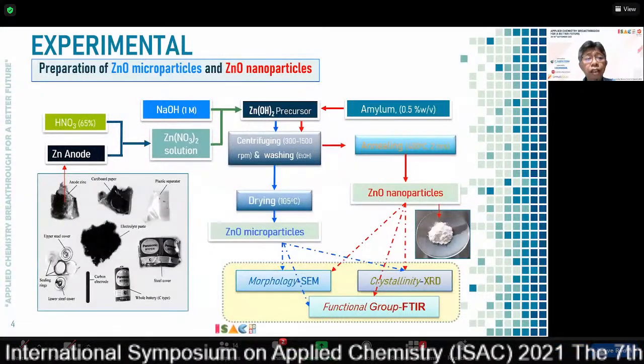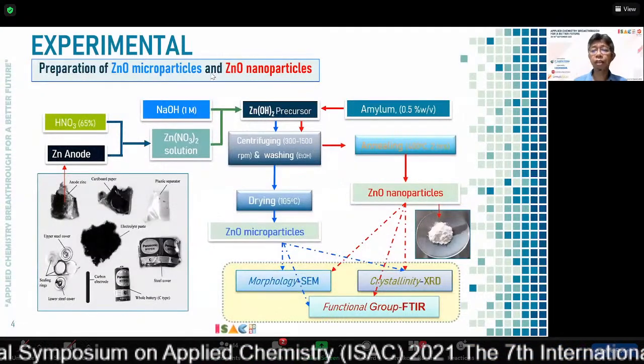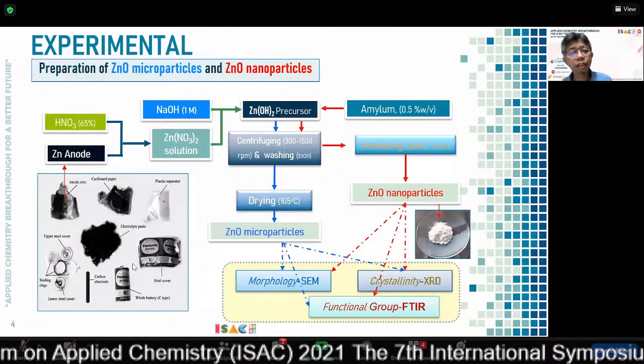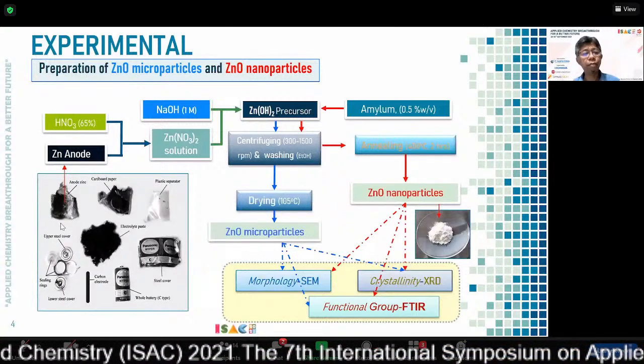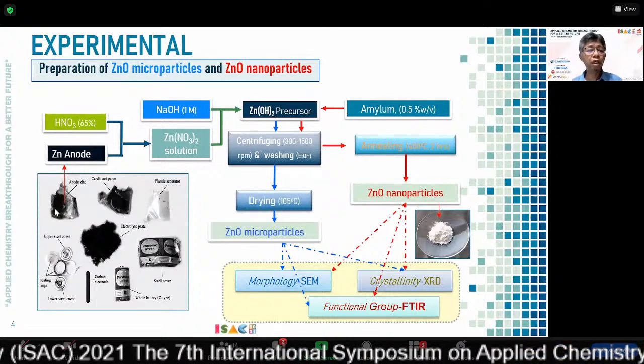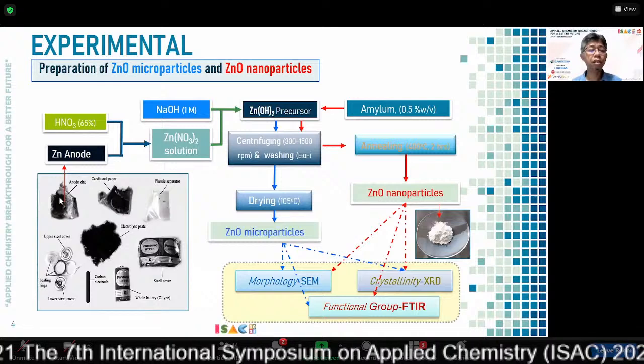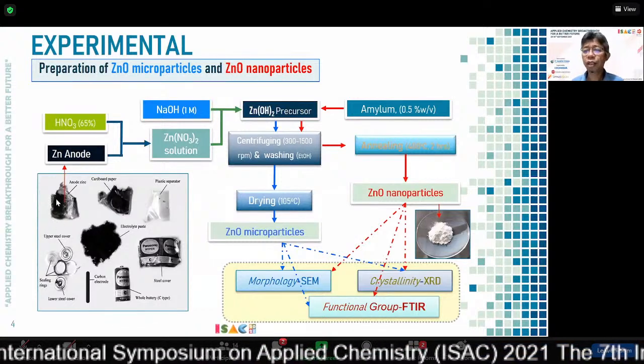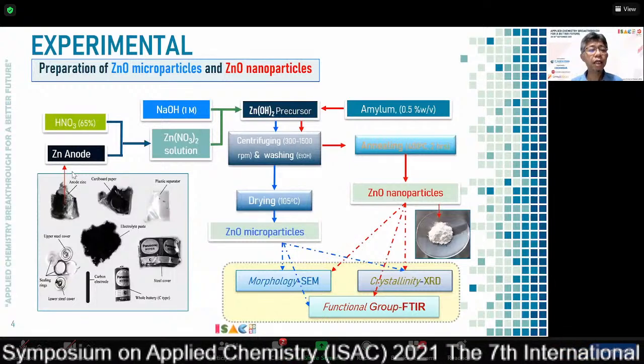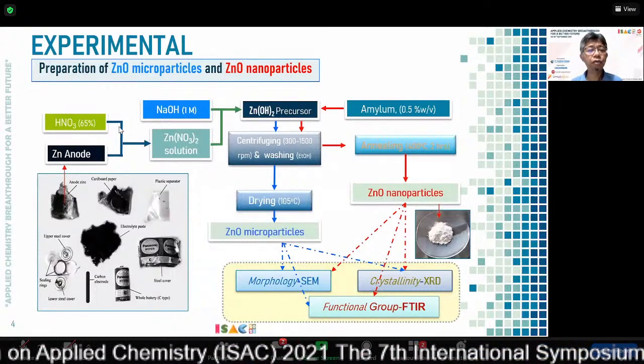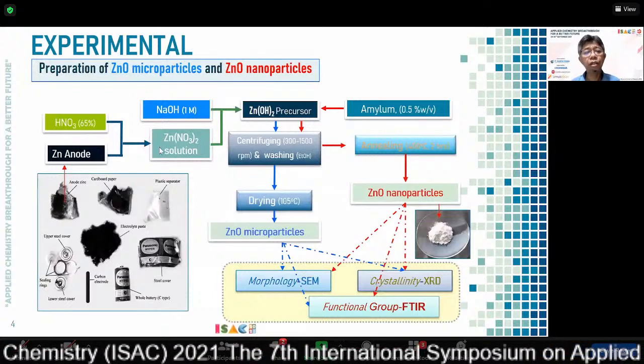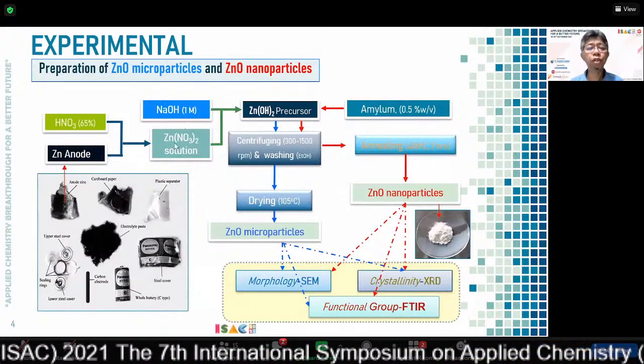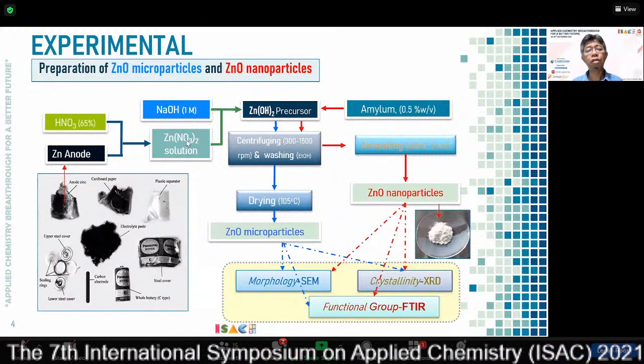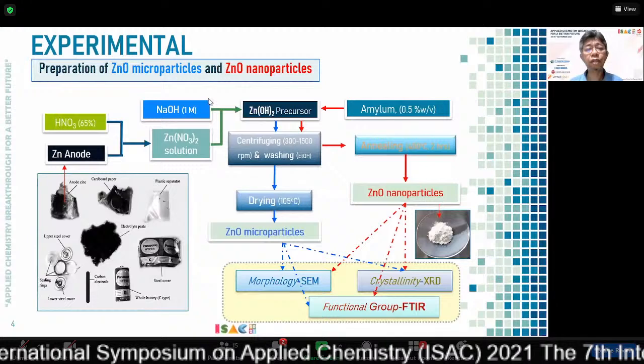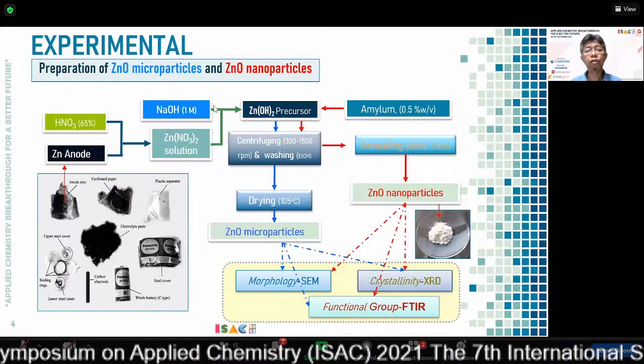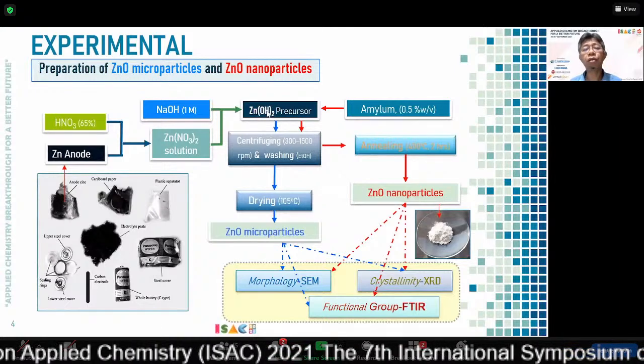If we look at the experimental here, how we obtain the zinc oxide microparticles and zinc oxide nanoparticles, let's see on the left side here that once we dismantle these spent batteries, we take and clean the zinc anode part, and we cut it into small pieces here, and then we react it with nitric acid in order to obtain the zinc nitrate solution. And then we neutralize up to pH 7 or even 8 by adding sodium hydroxide in order to obtain zinc hydroxide as a precursor.